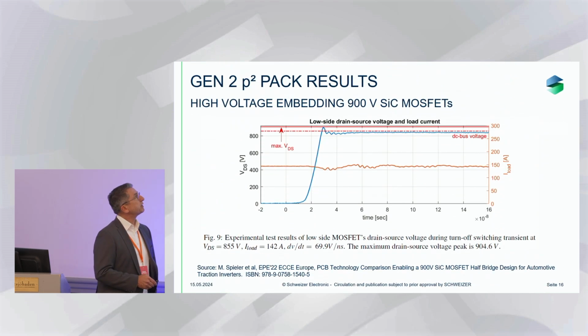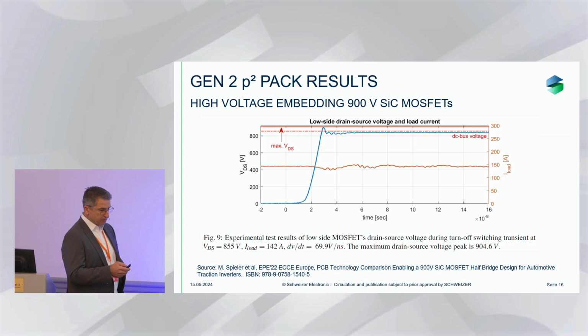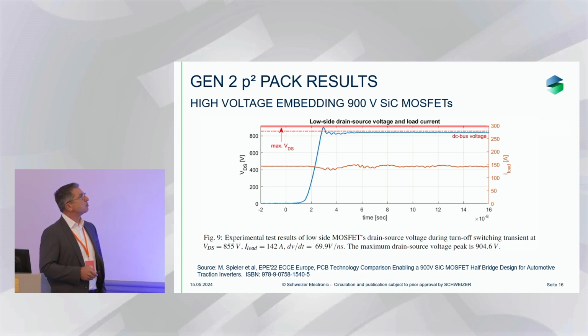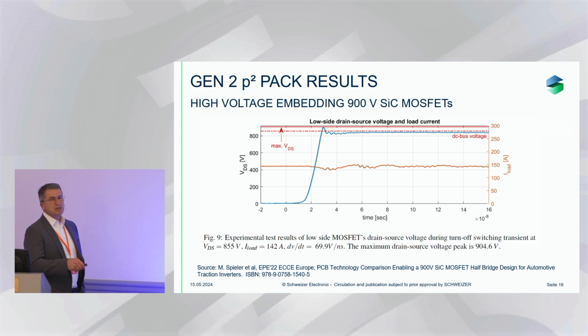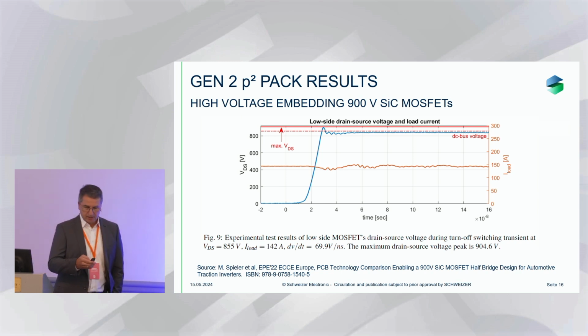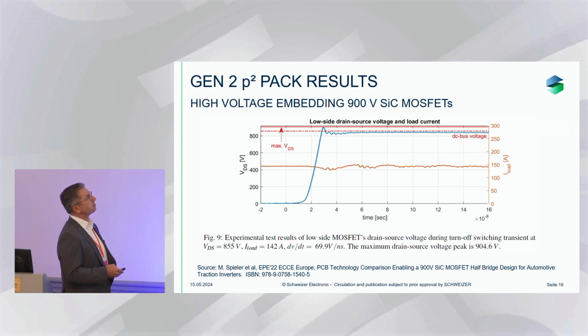And the following diagram points out this measurement. What you can see here, the rise time was approximately 70 volt per nanosecond, and here the overshoot voltage and the very, very little ringing after the switching. So very, very smooth switching. If you're interested in this paper, you can get it from us. So this paper showed that you could use 900 volt devices for 800 volt electrical systems. So you could make use of a lower RDS on.